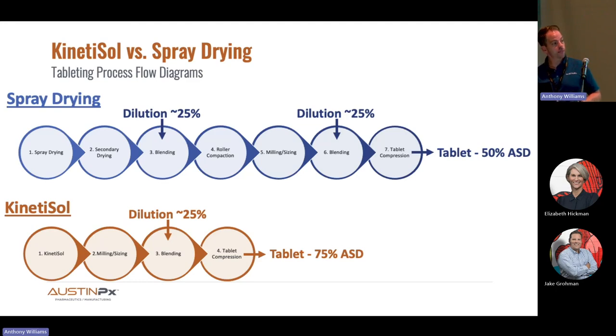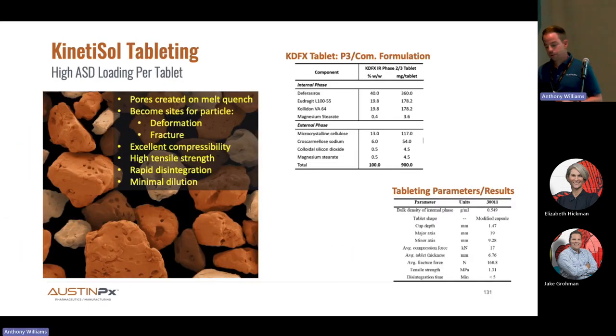So the final tablet, in many cases with KinetiSol, has about 75% ASD load, which can be, as I pointed out in some of the first examples, really critical in terms of reducing pill burden. And how are we able to achieve tablets with 75% ASD load? And in this case, the particles aren't blue. They came out of the mill orange, but that's not why they're compressible. The reason they're compressible, if you look at it, it's granules from a milling process. So under SEM, it doesn't look that much different than melt extruded granules coming out of a milling process.